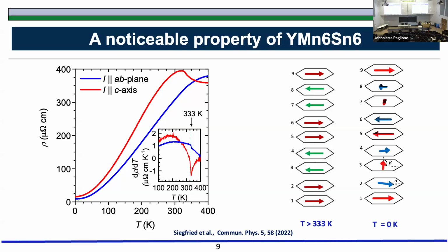So the spins are ordered like this, right? There are ferromagnetic spins here. They rotate slightly along this direction. So after 8 unit cells, it repeats along the c-axis. That gives you the spiral state. And as you can expect, it will be easier for electrons to move parallel to these spins; in the plane, the resistance is less in this case. And when these electrons try to move across this line, the resistance is higher here. It's perfectly normal, nothing unusual there. Okay, just looking at this.